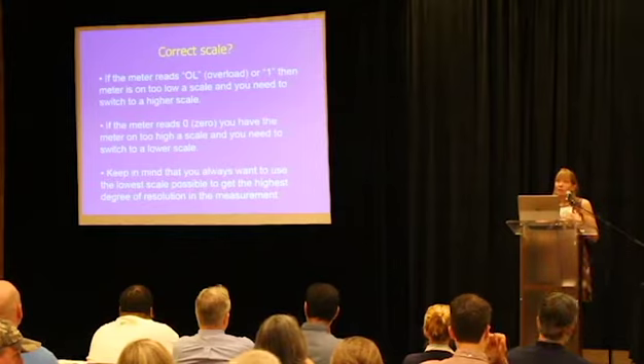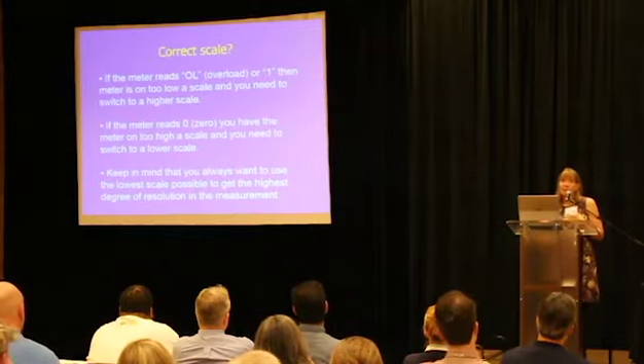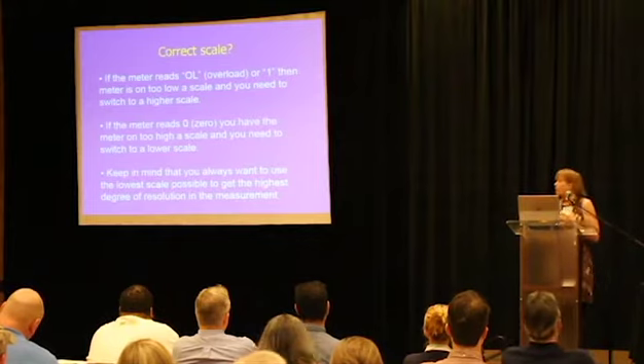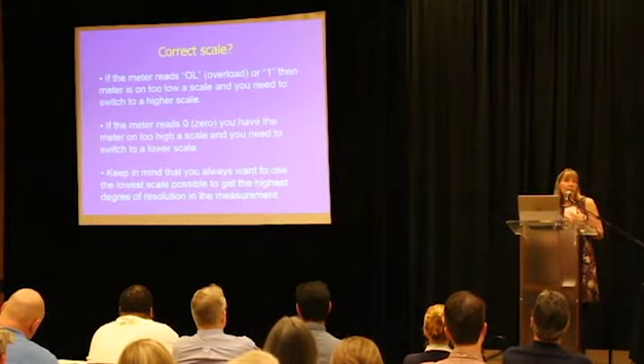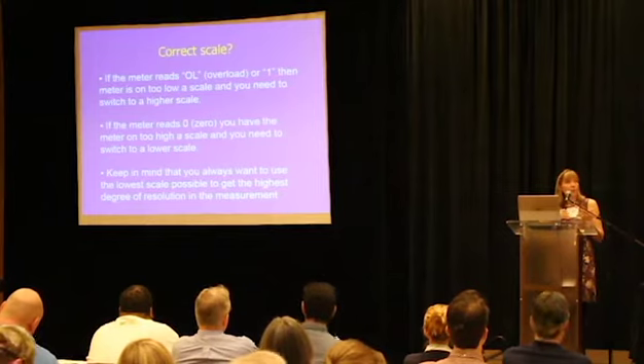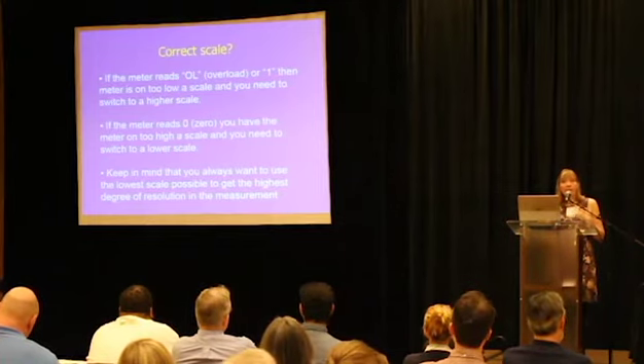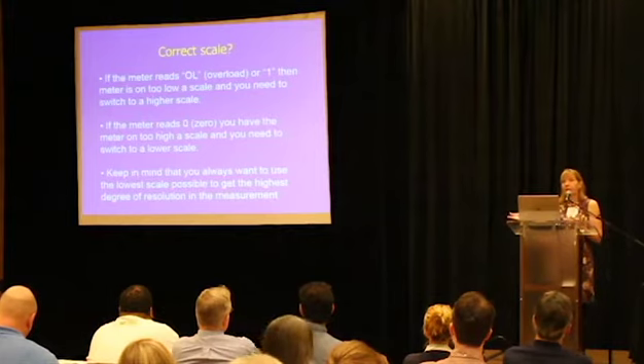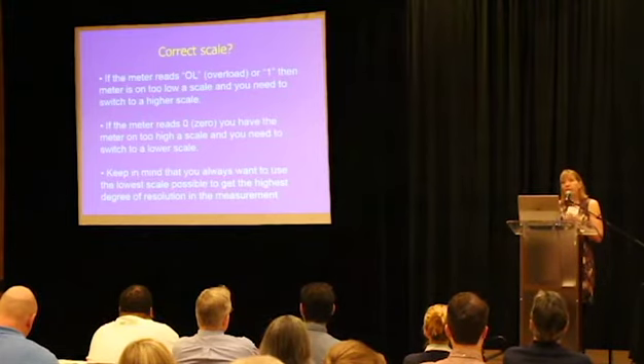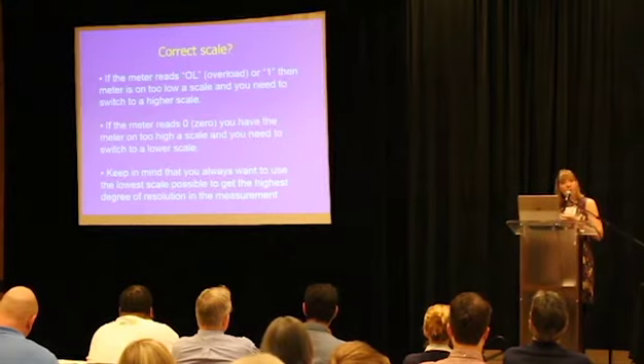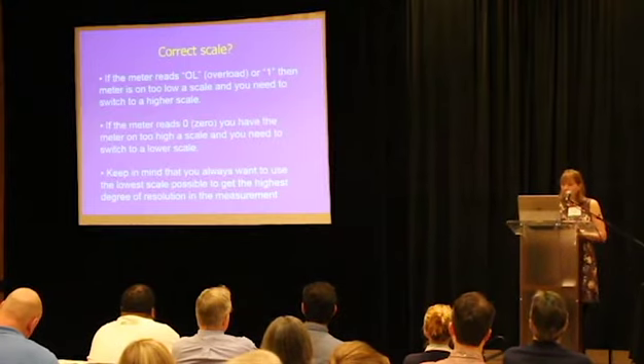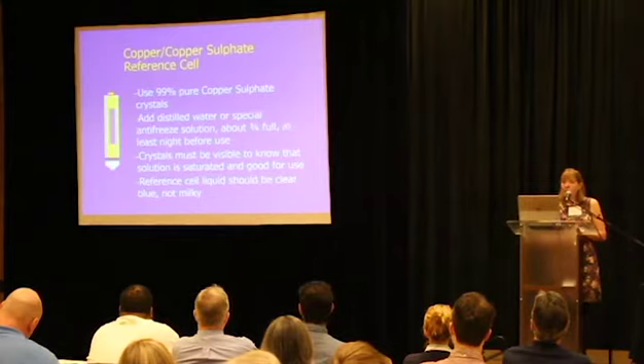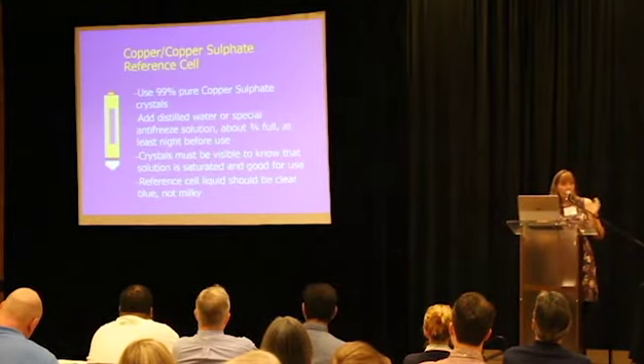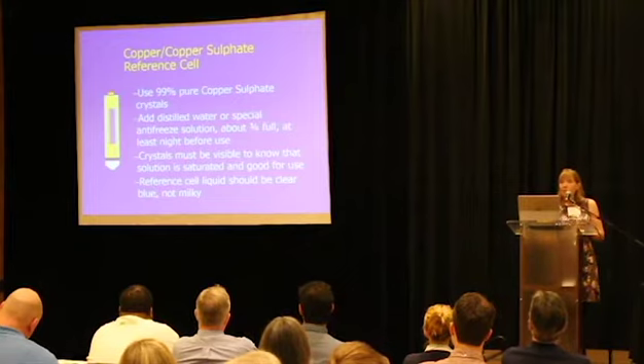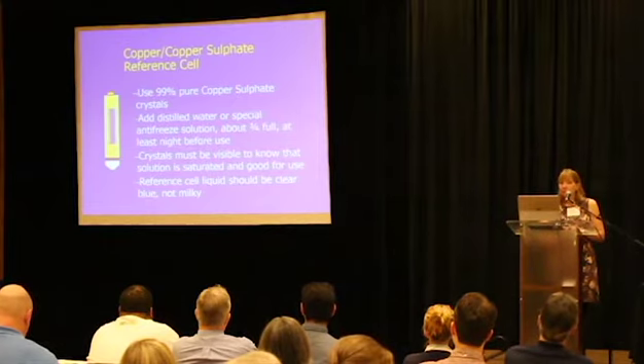We tell all our testers that all the equipment should be calibrated at least once a year. Reference cells actually should be calibrated more often than that, and that depends on how often they're being used. Have they picked up any contamination? If they're out at a site that's heavily contaminated, that gasoline or fuel at the site can actually get soaked up through that porous tip. So when they're going to recalibrate, they want to use pure copper sulfate crystals. They want to use distilled water. Again, this is to eliminate any sources of error.